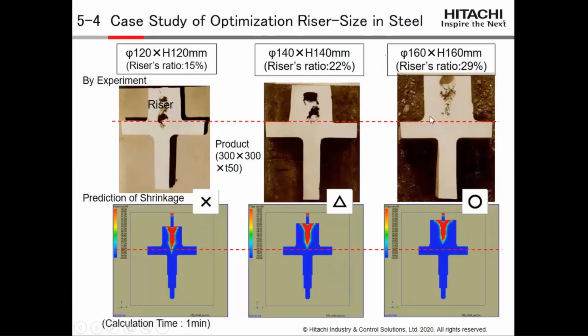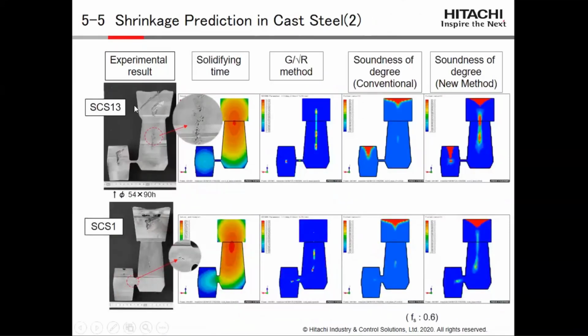Certainly, there is a trade-off between the size of the riser and shrinkage porosity. We can clarify the relation of this trade-off by evaluating with ADSTEFAN simulation. So in shrinkage prediction in cast steel, it shows the experimental result. It is happening here and here.